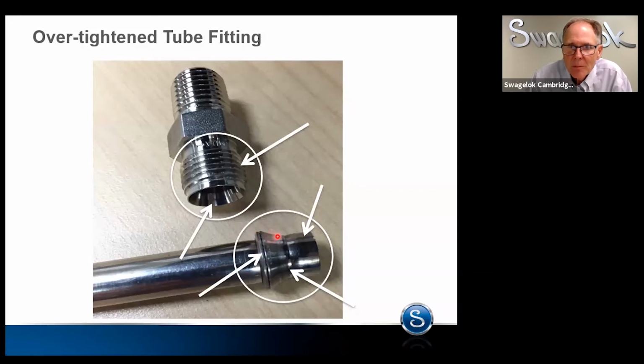Then, if you look at the metal right here, we've lost the conical shape of the Swagelok front ferrule. We've actually deformed it into a bell shape. We've taken the elasticity out of the metal. Not a good thing. You're not going to get a good reseal. So you want to make sure you don't severely over tighten. Another check. You won't be able to check by really looking at the body bevel, because it's just going to look good because everything drives straight in and straight out if you're always supporting the body hex. But what you're really going to notice is on your threads.